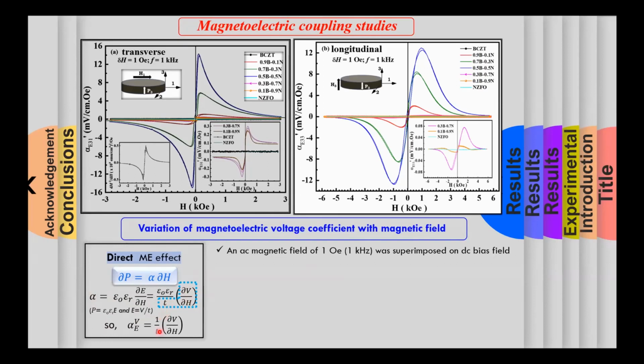Here, this term, the inverse of thickness and the magnetic field derivative of voltage, is known as the magnetoelectric voltage coefficient, and it is this voltage coefficient which is experimentally measured, and it has the units volts per centimeter oersted. So in magnetoelectric coupling studies, we measure the magnetically induced magnetoelectric voltage. The measurements were performed in two modes, transverse and longitudinal. In transverse mode, the magnetic field was applied perpendicular to the polarization direction, whereas in the longitudinal mode, the magnetic field was applied parallel to the polarization direction.